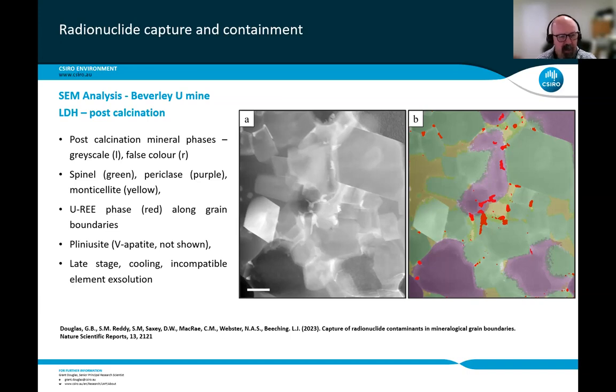And then what we saw was a really interesting uranium rare earth phase in the red that predominantly occurs along the grain boundaries. We also have pliniusite, which is a vanadium-rich apatite, which we haven't shown there. But what we're actually thinking here, as we'll show later, is that this is due to what's known as late-stage cooling and incompatible element exsolution. While this sample is up at, say, 1,000 to 1,300 degrees, you can accommodate the uranium and the rare earths, the larger ions, within these open crystal structures. But as you start to cool, the crystal structures start to close down. Uranium and rare earths have got nowhere to go, so they are exsolved from these crystal structures, and then they end up as interlayer phases that occur between the other major mineral components in this calcined layered double hydroxide.